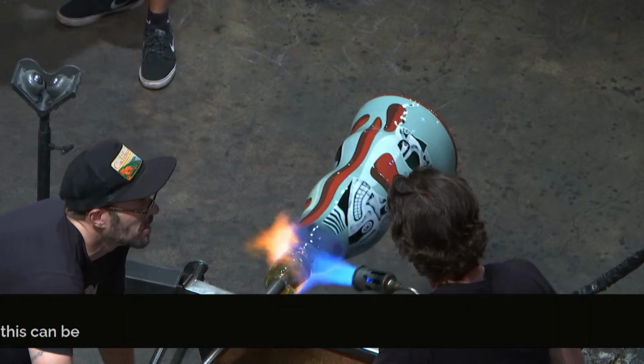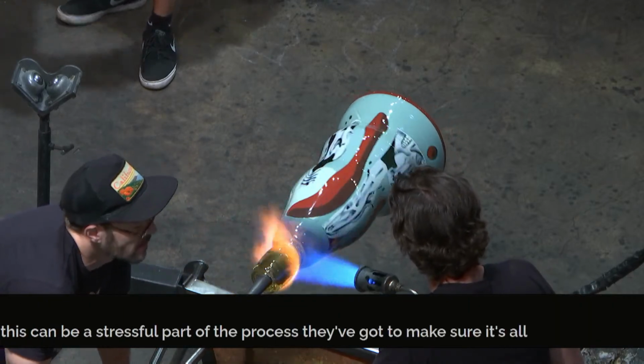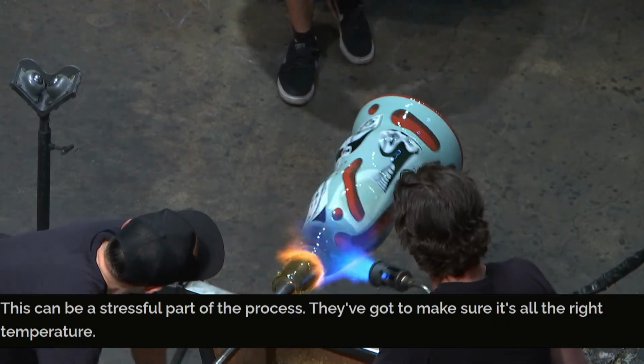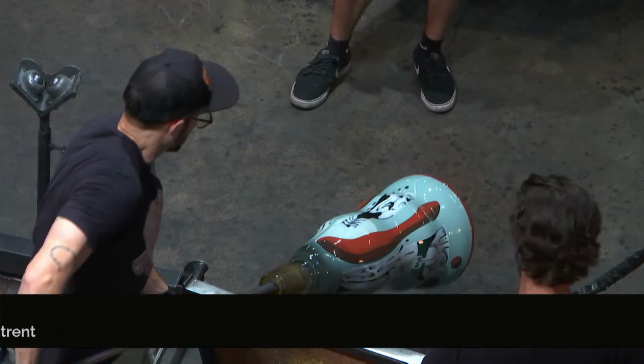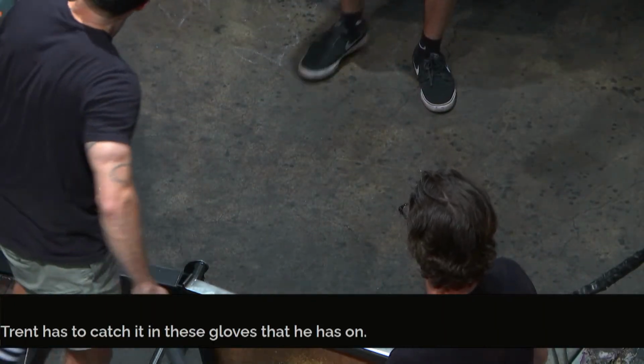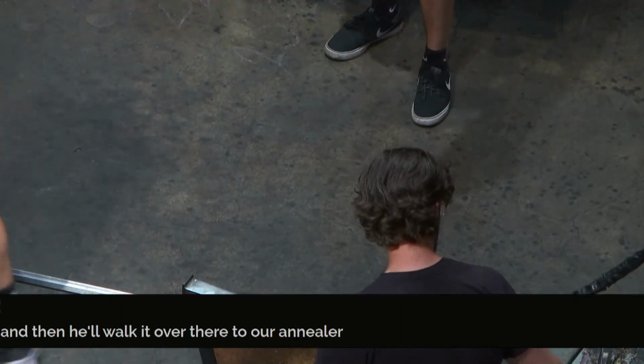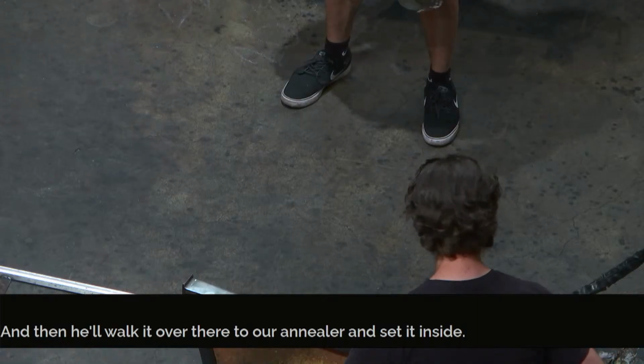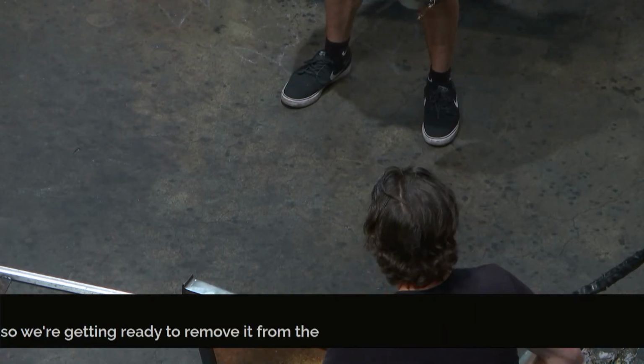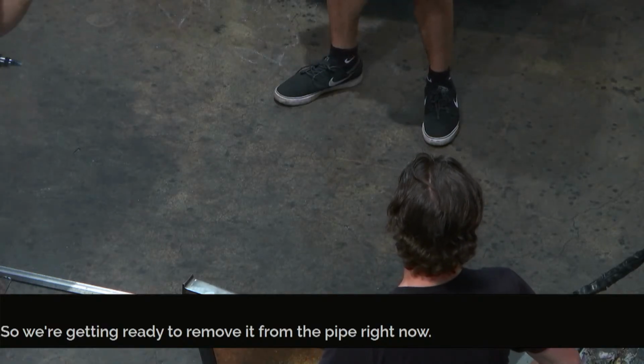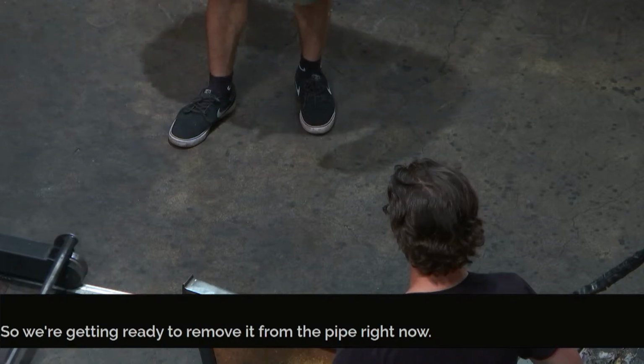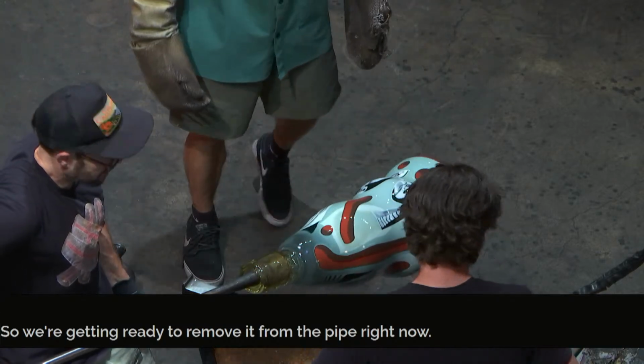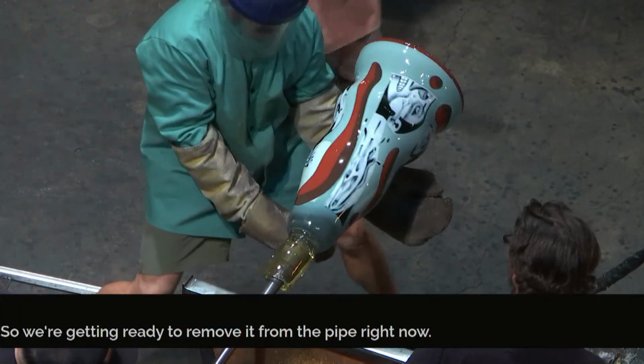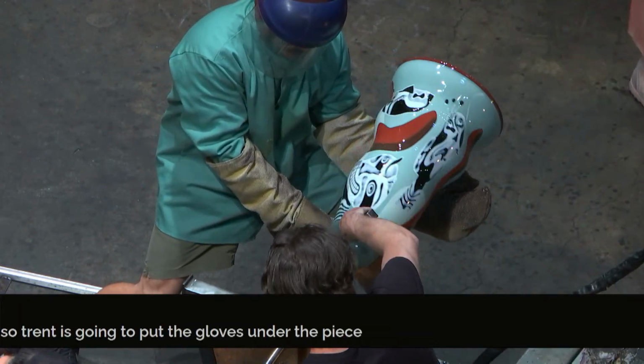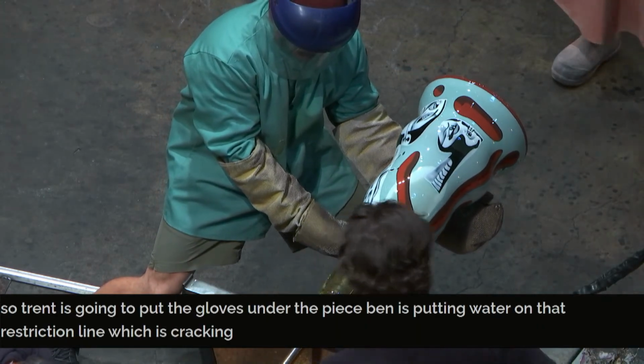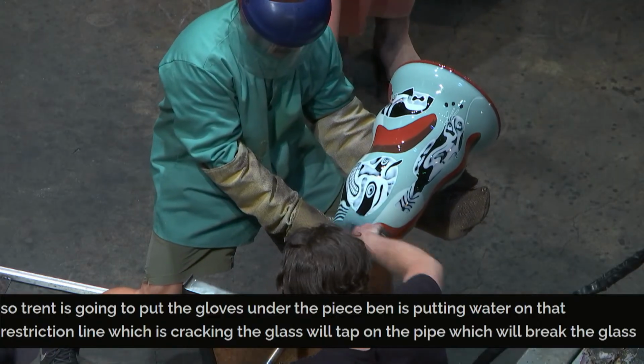This can be a stressful part of the process. They've got to make sure it's all the right temperature. To get that off of the pipe, Trent has to catch it in these gloves that he has on, and then he'll walk it over there to our annealer and set it inside. So we're getting ready to remove it from the pipe right now. So Trent is going to put the gloves under the piece. Ben is putting water on that restriction line, which is cracking the glass. We'll tap on the pipe, which will break the glass where he's putting the water.